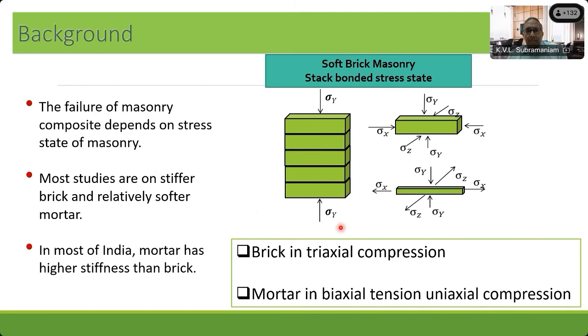And the primary concern, if it is a load-bearing wall, is the gravity load, which would essentially produce a compressive state of stress in the masonry. Now, it's a composite material. When you look at this, what happens typically in stiff brick masonry is that brick is stiffer than the mortar. So the brick has a much higher modulus than the mortar.